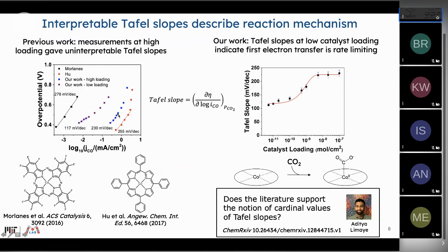If one then goes to a higher loading, reflecting what's typically happening in many literature reports, one finds a Tafel slope of 230 millivolts per decade. So we can see in our own hands how loading can obscure the intrinsic Tafel slope in the system. One can systematically chart this out. Here, plotting the Tafel slope as a function of catalyst loading, and you'll see it starts very high on the right-hand side, and as you go to lower and lower loadings, it comes down and plateaus at around 120 millivolts per decade.